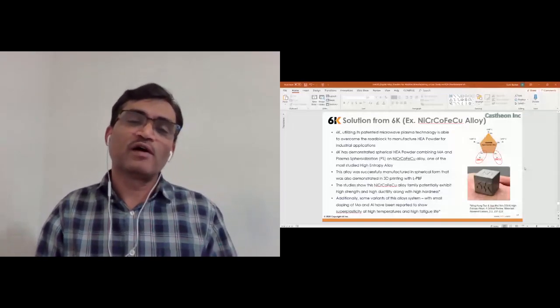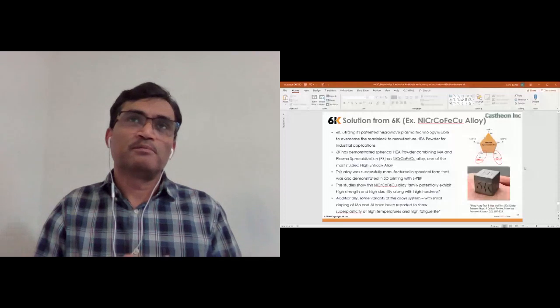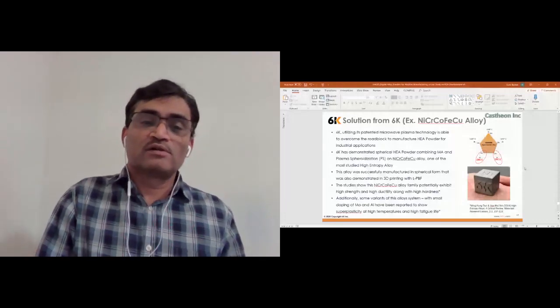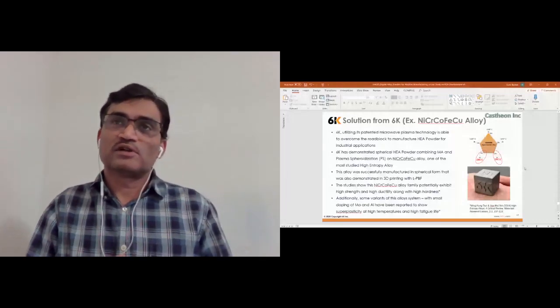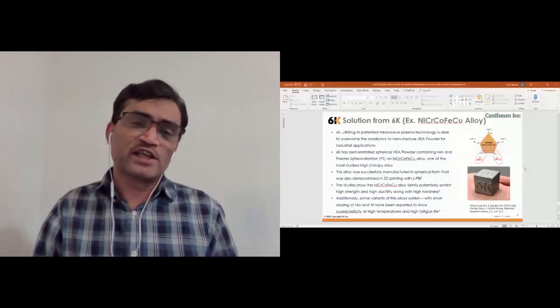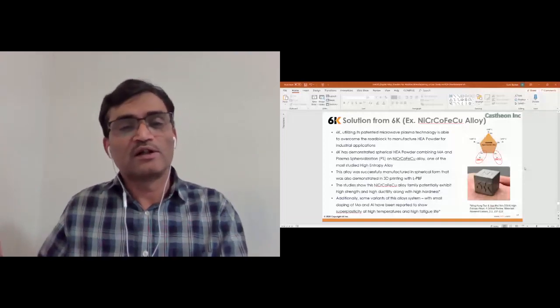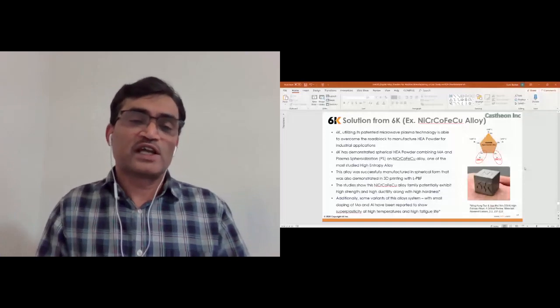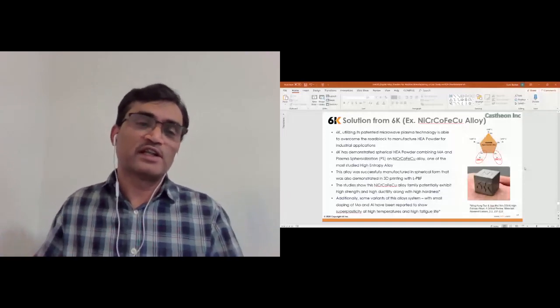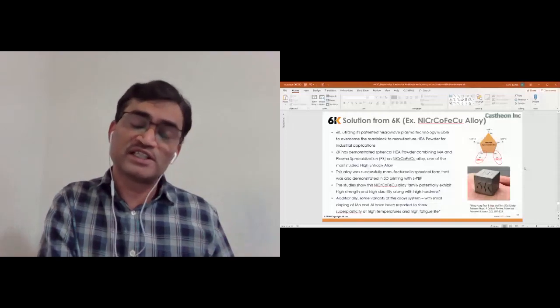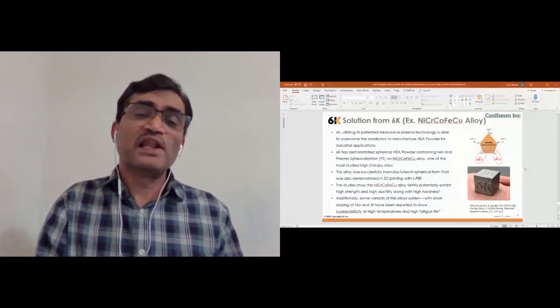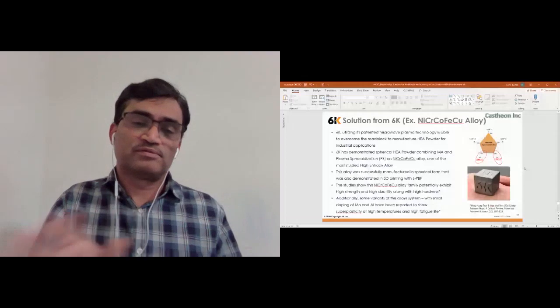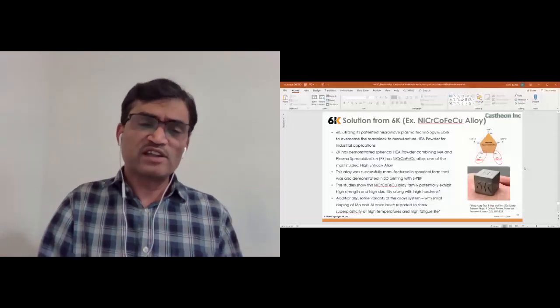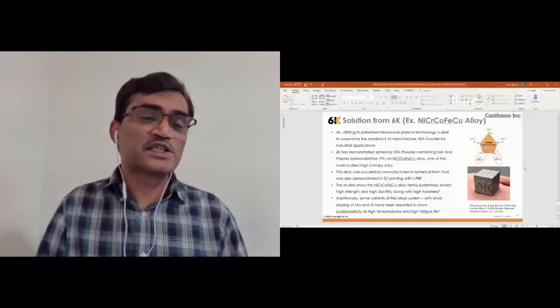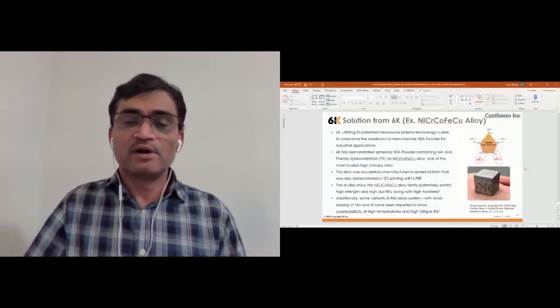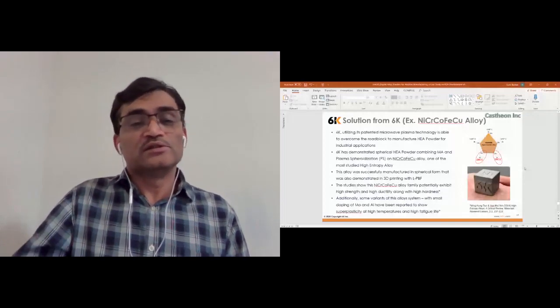So we have taken this alloy and tried to make it in spherical form. We have done mechanical alloying, and at every stage we are tracking the alloying with an XRD plot, and that's how we decided the milling time for mechanical alloying. And then we have used our Unimelt system to spheroidize this powder, and we did that.